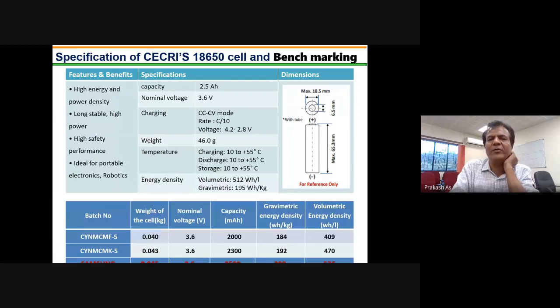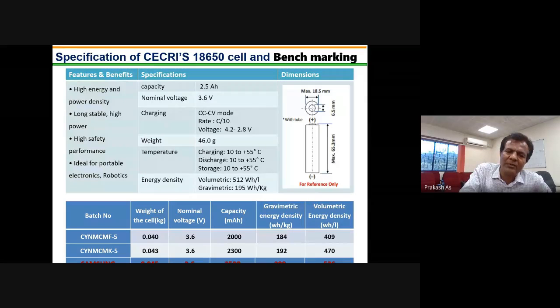As you can see here, just to give you an idea of where we stand, the bottom one is a cell from Samsung. They are about 45 grams and 3.6 volt and 2.5 ampere hour. Presently with NMC, a similar chemistry, we have reached a capacity of 2.3 ampere hour. So energy density is 192. So we are almost there at the commercial level, volumetric is 470 and this is about 526. We are almost there, and with some other chemistries we are able to meet the benchmark of commercial cells from LG or Samsung or wherever.